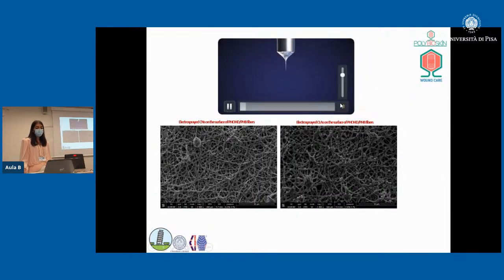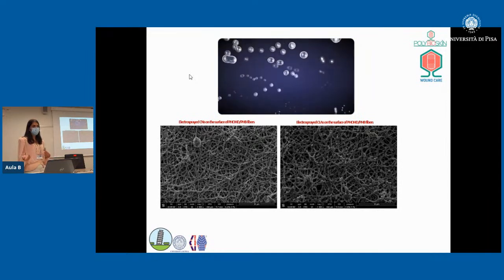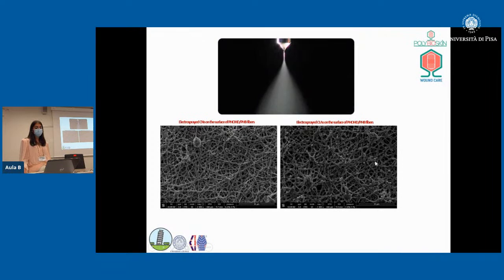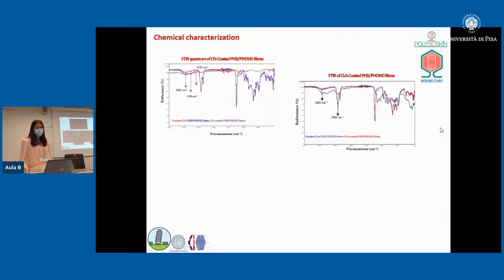In the next step, in the optimum condition, we tried to use the electrospray technique to functionalize the electrospun fibers. We had polyhydroxyalkanoate as substrate, and we electrosprayed chitin and chitin-lignin complex on the surface of this nanofibrous mesh. And as you can see, they could be successfully located on the surface of the mesh, and they kept their size and their morphology.